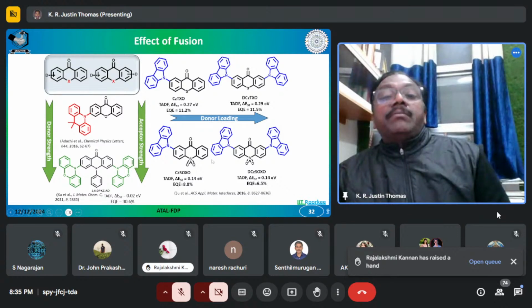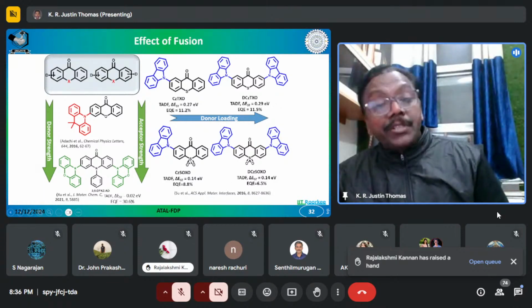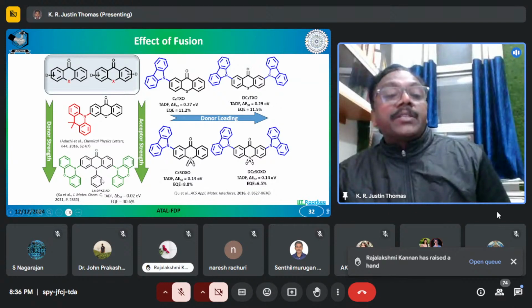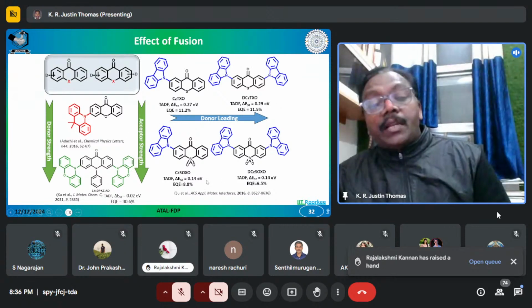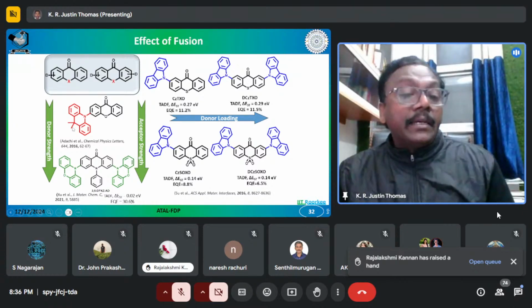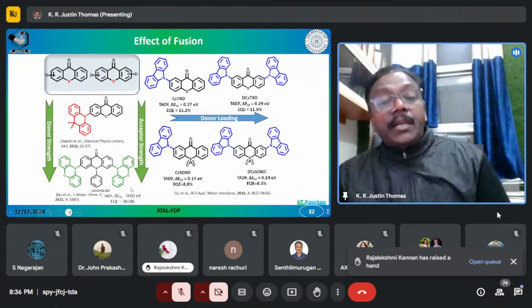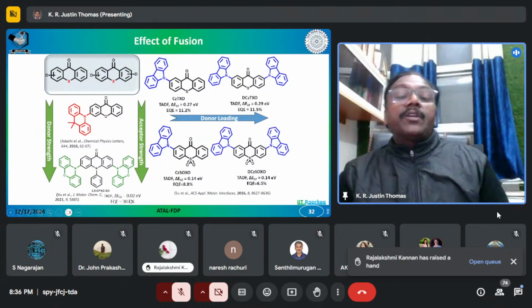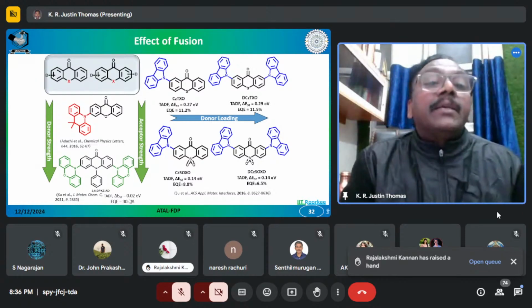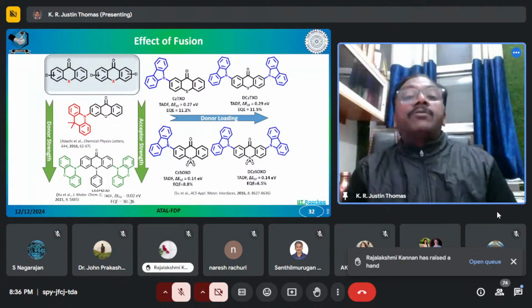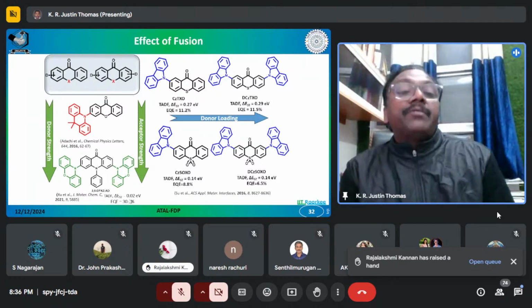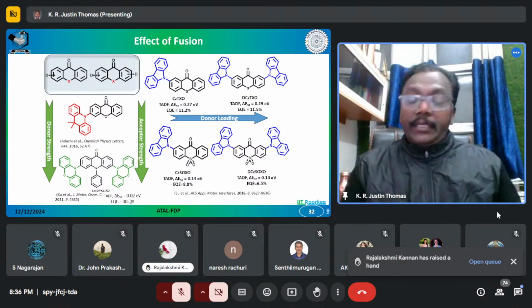When you increase the number of carbazoles, it has less effect on this system. And at the same time, when you oxidize the sulfur here, you reduce the delta EST further. However, the efficiency decreases. And if you increase the donor strength by replacing the oxygen with nitrogen, you decrease the delta EST and increase the efficiency. So there are two aspects: either increase the acceptor strength to reduce the delta EST at the cost of efficiency, or increase the donor strength to reduce the delta EST and increase the external quantum efficiency. So what we have learned here is that by fusing the benzophenone with a heteroatom, you can now have TADF, irrespective of the number of donors or strength of donor.